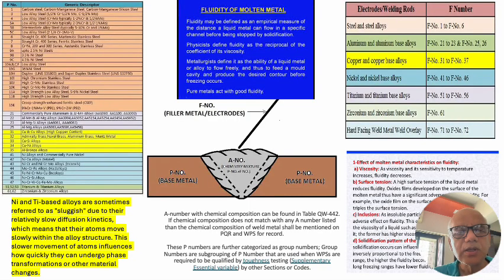That means this solid line here and the dotted line, which is the initial edge preparation, this is the distance or thickness the penetration is going to melt of the parent metal, which has a particular chemistry. The F number comes from the consumable, which has another chemistry or maybe the same chemistry, and depending upon the dilution. So for example, let's say that at both ends we have a dilution factor of 10%. That means the resultant weld metal is going to be 80% of the filler wire or the electrode composition, and 20% of the resultant weld metal or the A number is going to be from the